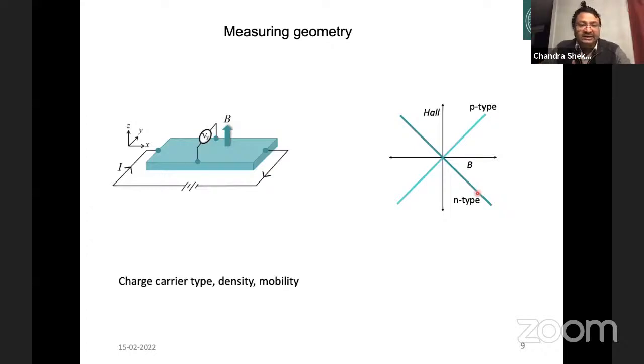Not only the type of charge carrier, we can also calculate the density of the charge carrier. We can also calculate the mobility of the charge carrier, how fast an electron or hole is moving inside the material. This simple effect is very useful to measure the physical properties of a material, which is very common for transistors. When we dope silicon to make it N type or P type, and how much we are doping, we can just measure the Hall voltage or Hall resistance and calculate how much density is inside and how fast the electron is moving.